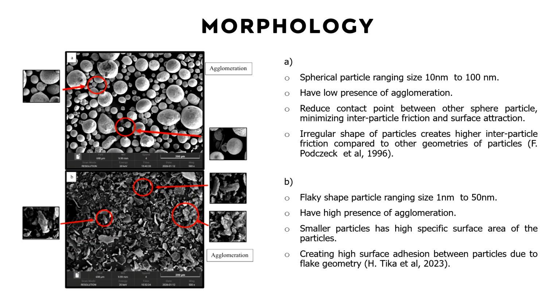In terms of the morphology, these are the particles for the filler that we used in the compound, the hybrid filler used within the LLDPE conductive polymer composite, whereby the spherical one is the copper particle, and at the bottom the flaky and agglomerated one is the graphite morphology.